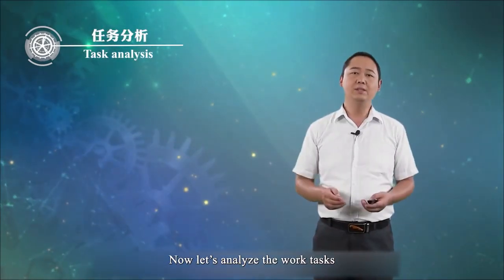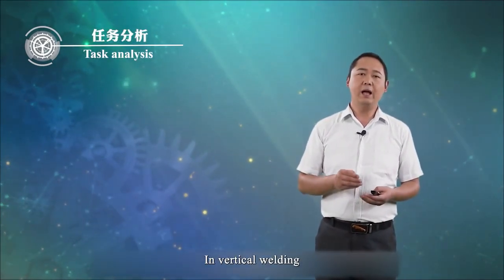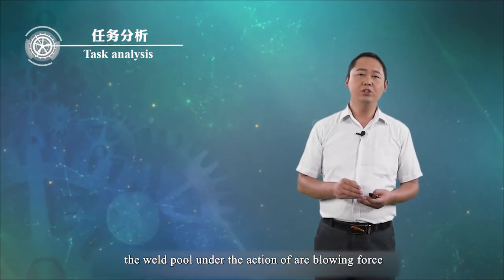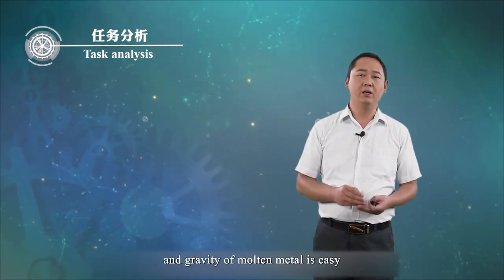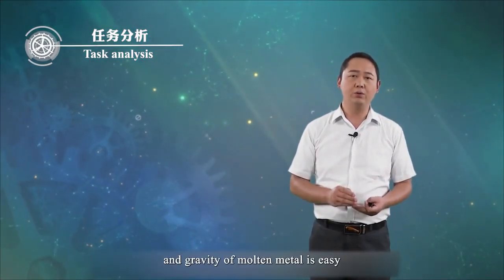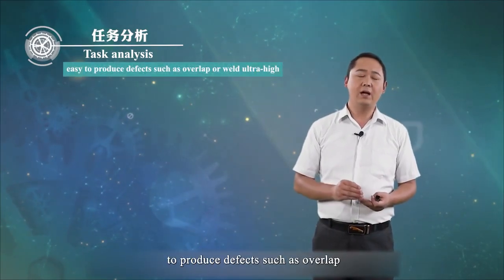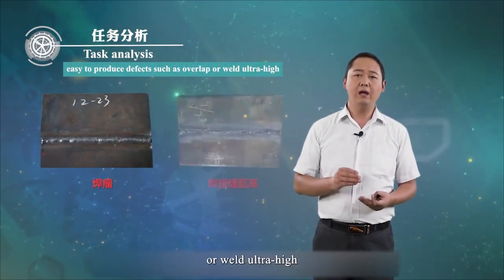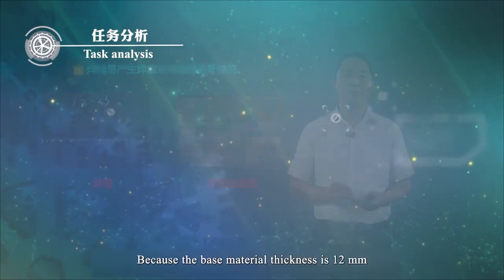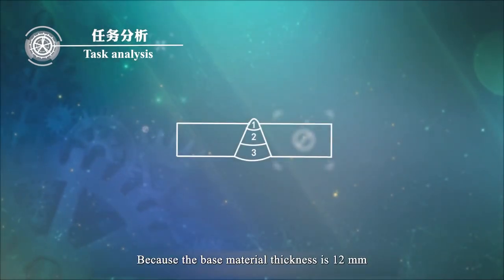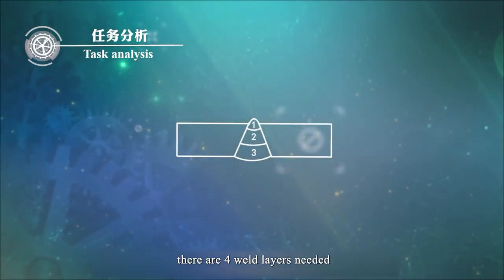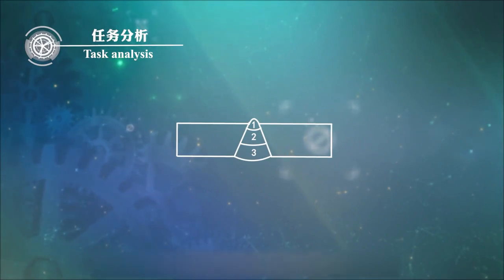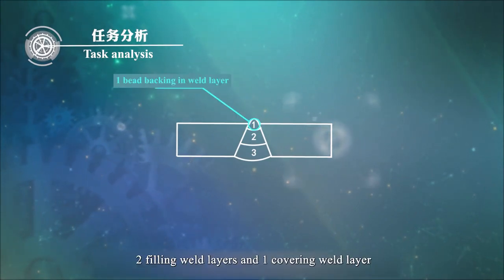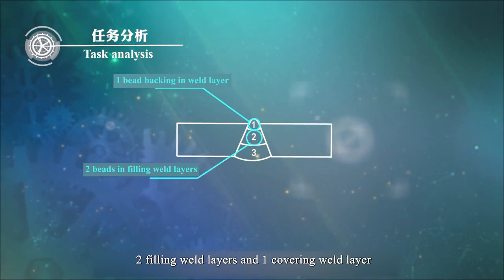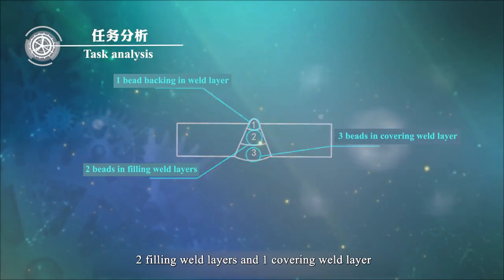Now let's analyze the work tasks. In vertical welding, the weld pool under the action of arc blowing force and the gravity of molten metal is easy to produce defects such as overlap or weld ultra high. Because the base material thickness is 12 millimeters, there are 4 weld layers needed: 1 backing weld layer, 2 filling weld layers, and 1 covering weld layer.